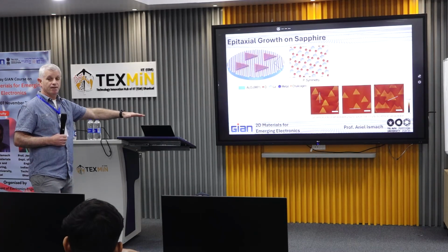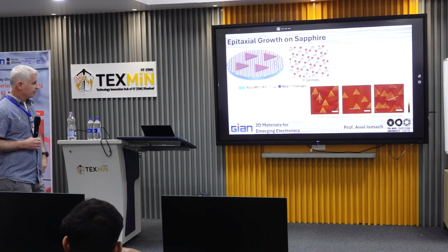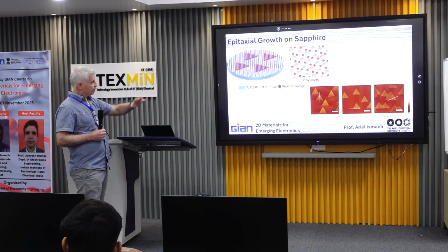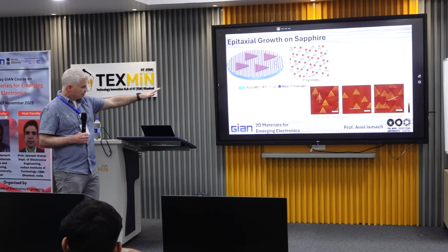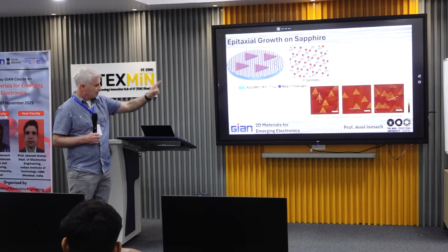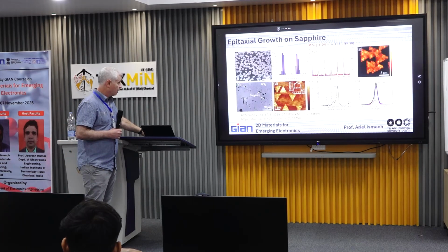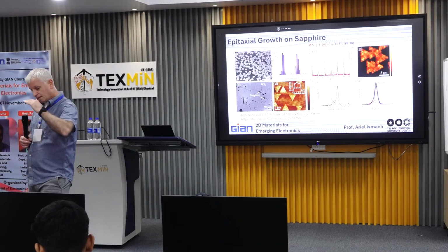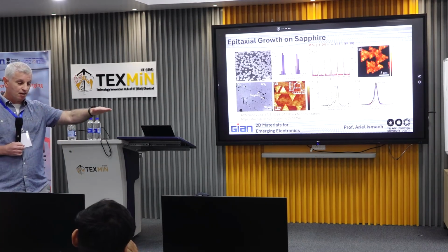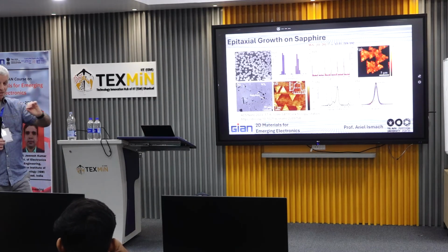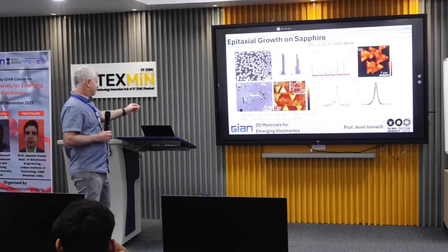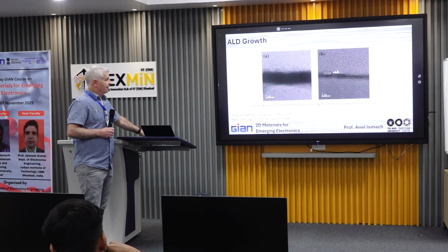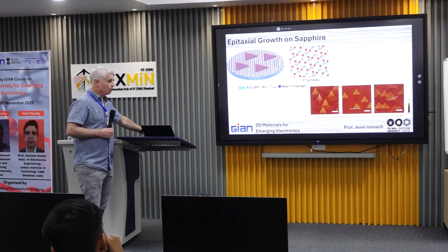They modified the surface with an atomic layer of lanthanum, and that breaks the symmetry of the sapphire, so it orients only along one direction. By the way, in our paper, we show that we can modify the surface of the alumina, the sapphire, with an atomic layer of tungsten. So they did something similar with lanthanum. Anyway, interesting. Questions so far?